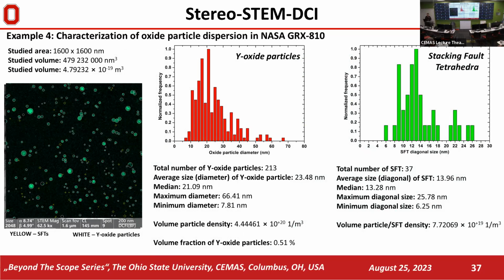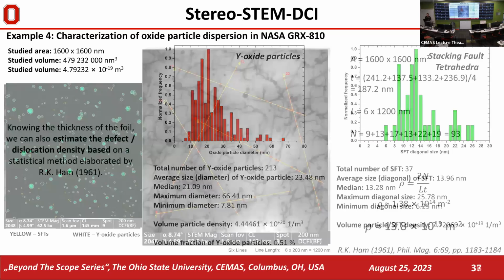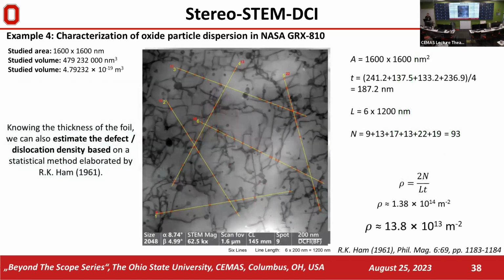You can estimate what's in the initial state already, like Taylor strengthening and Orowan strengthening factors for these alloys using this technique. Another thing which this foil thickness measurement and stereo microscopy can be used with is the estimation of defect and dislocation density.